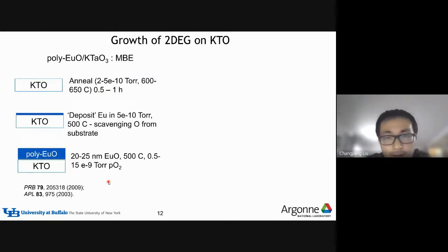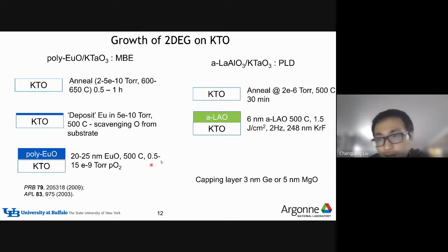So now in our case, we just grow an oxide interface using either molecular beam epitaxy or MBE, and also the pulsed laser deposition method or PLD. In both cases, we deposit an oxide insulator on top of KTO. So for the MBE, we deposit a polycrystalline europium oxide on KTO. And eventually, at the interface, we found that the interface becomes metallic.